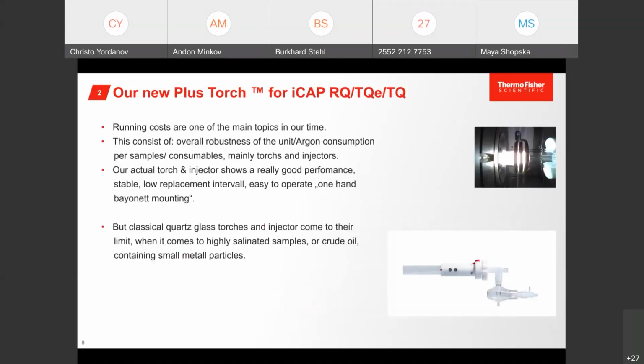So next, for our ICP-MS part, we recently introduced a brand new torch. Our existing torch is a quite good torch, this quartz glass torch, originated from our optical ICP in Cambridge. We first launched this kind of torch with the iCAP 6000 series in 2006. It's doing everything, it's performing like the torches of our friends, meaning competition, but quartz glass has some limitations. When it comes to challenging matrices, like salinated samples, crude oils, especially crude oils with metal content inside, it comes to the limit.